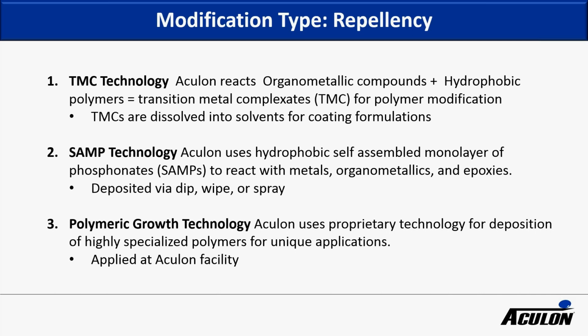The next technology we have is SAMP technology. It's based on self-assembled monolayer of phosphonates. Here we're utilizing phosphonate chemistry to react with oxides. So mainly these formulations are used for treating metals. They can also treat organometallics and epoxies. They're also dissolved in solvents, and so they're deposited by either dip, wipe, or spray.